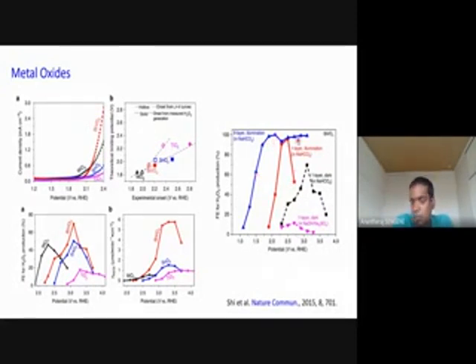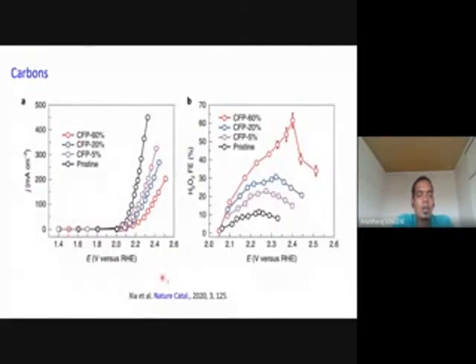So this material without photons is good, but when we apply a light, it still improves its activity to a higher level, and particularly for H2O2 selectivity. This work was recently published by Shi in Nature Communication, following which they also did one more work on carbon fiber paper, which is a very common substrate electrode in electrocatalysis.